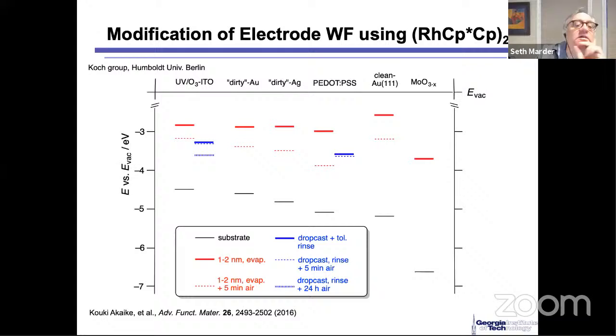The second thing is that when you actually put this in air, for a bunch of these, with the exception of the PEDOT, which can probably de-dope, it stays relatively low. And your solution doping is not quite as good as the vacuum doping, but it's not bad.